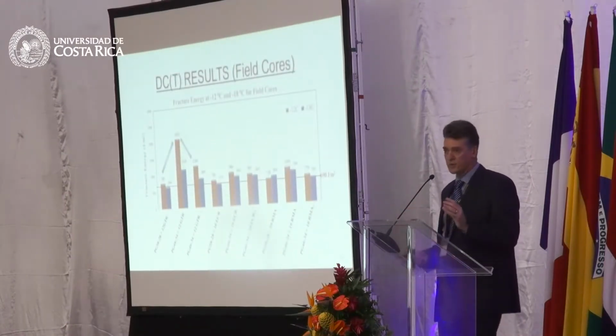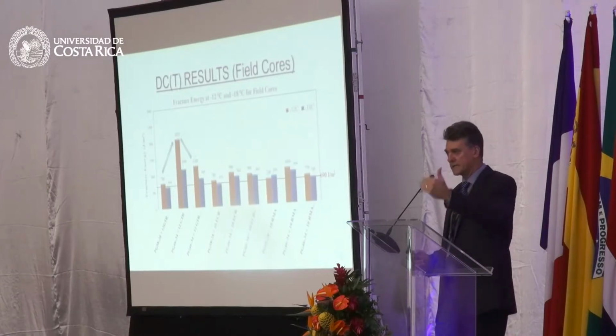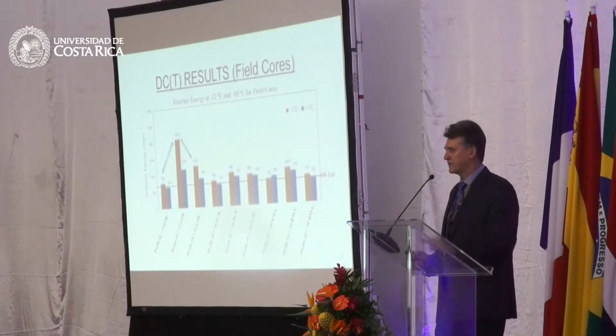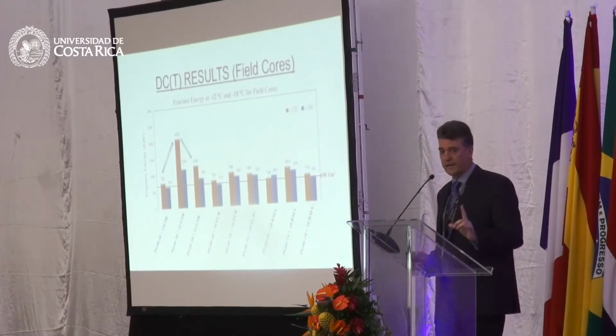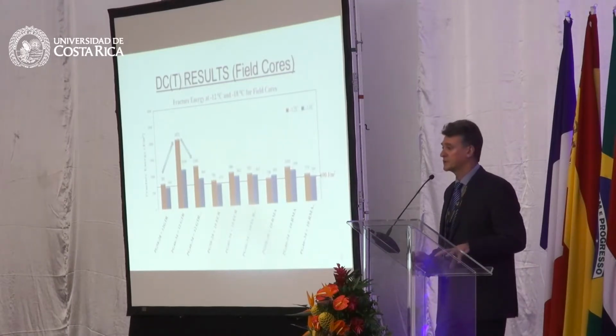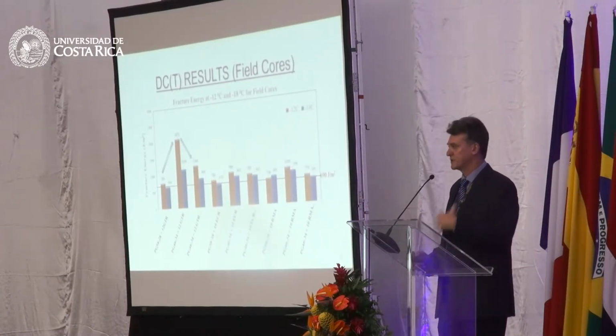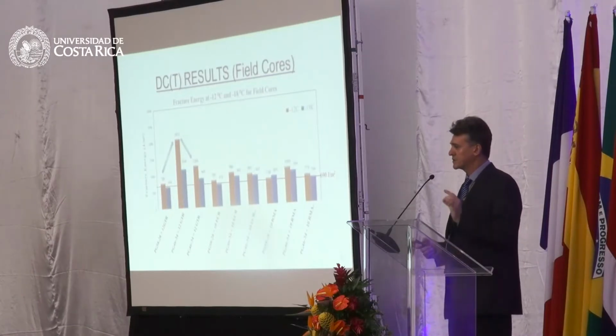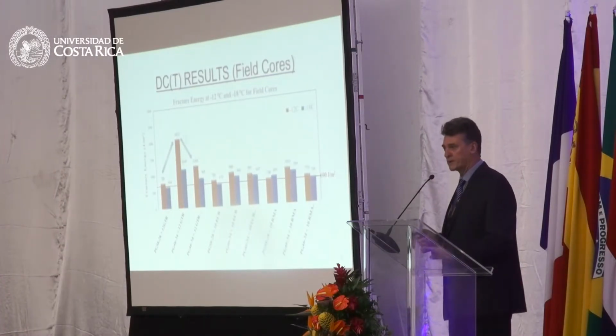When we tested the field cores, it was interesting that we actually had slightly higher fracture energies when they finally produced these mixtures. That's good. Sometimes in production, you'll see the performance properties go down as the contractor rushes to complete the project. It's not as good. But in this case, we had better properties in the field.